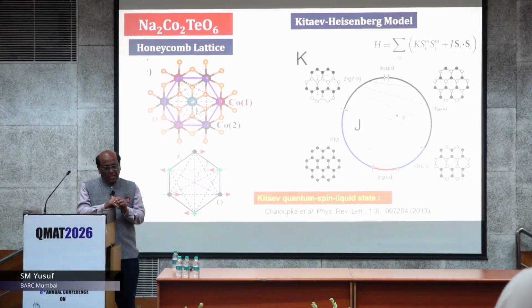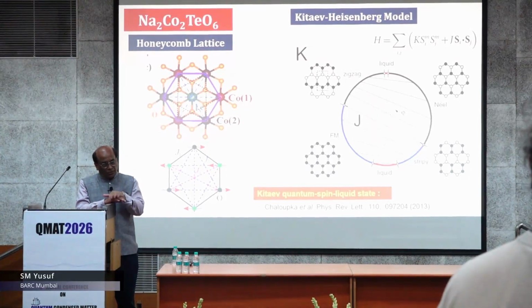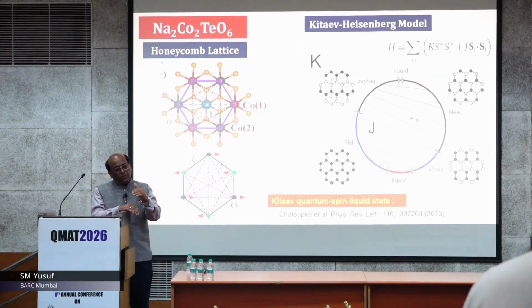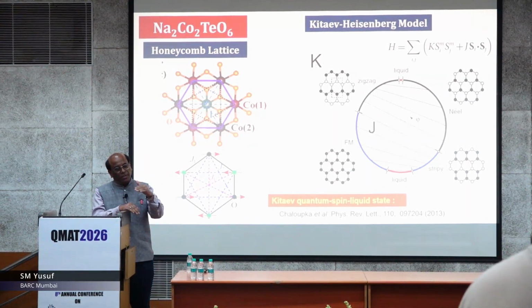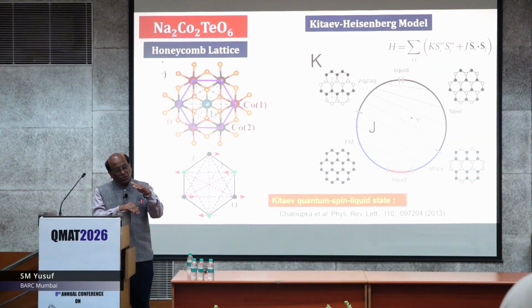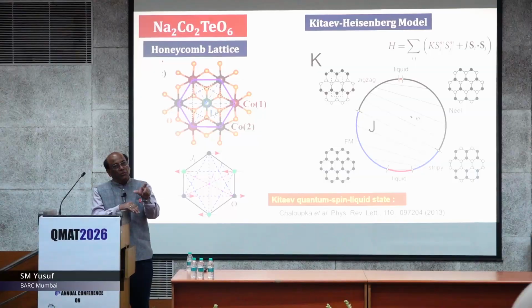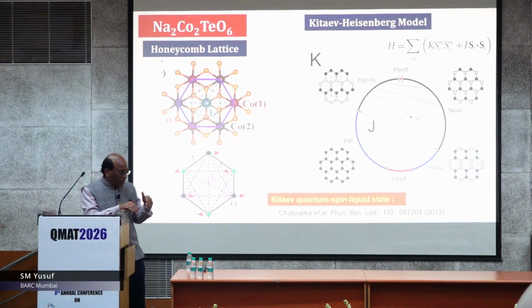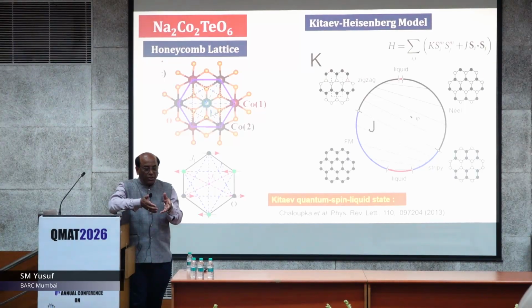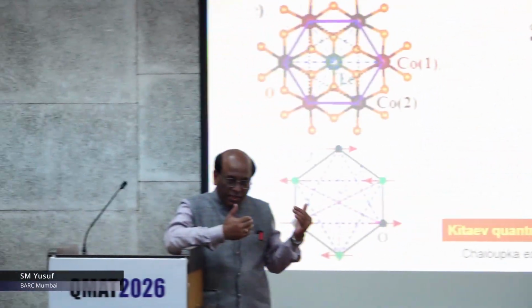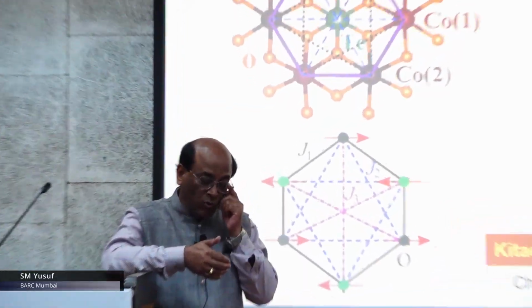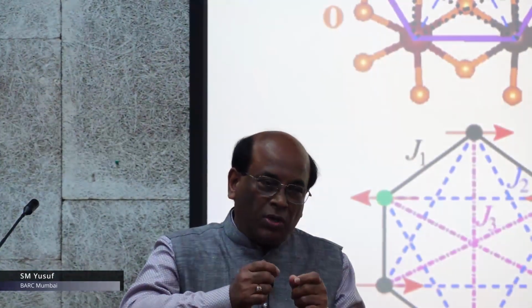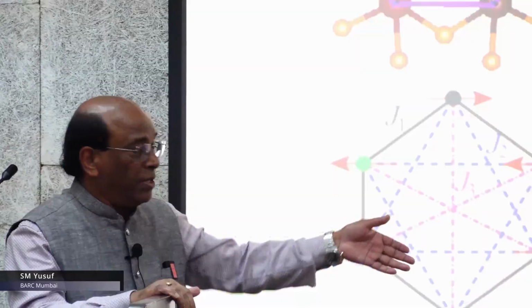What we have done is inelastic neutron scattering, which I did not present. There we have shown the magnetic transitions, and we have established that indeed the ground state of the cobalt is J effective equal to half, due to spin orbit coupling. This is one important point: can we have this kind of feature in a 3D system? This is the experimental confirmation that in this 3D system of cobalt we could have J effective half, not by spin but by spin orbit coupling. And if J effective half is the ground state, then what kind of magnetic excitation do we expect? We have got those transition lines which I did not present, but I have the slide maybe somewhere.